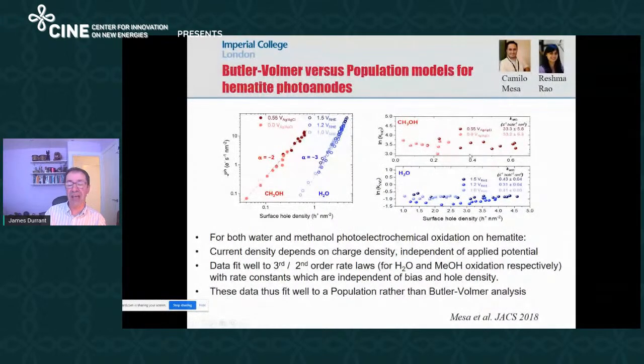Another way of looking at data here is these are plots of the rate constant for water oxidation measured for different applied potentials and different surface hole densities for both methanol oxidation and water oxidation. And essentially what we find is that we can measure a rate constant for methanol or water oxidation, which is independent of potential and surface hole density. They fit rather well to the simple third and second order rate laws. And that suggests to us that this population model is indeed an appropriate way of analysing the data and not a far more widely applied Butler-Volmer analysis.